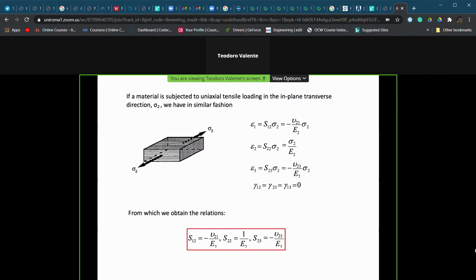If instead we are going to apply a tensile load in the transversal direction, that is in direction number 2, we do have, again in a similar way, the possibility to define the 3 strains according to the 3 axes 1, 2, 3, a shear coupling again not being present. And so what is leading now is this expression, which comes again from the application of the linear Hooke's law, and then the possibility to have the contraction in the other directions defined by the relative Poisson ratio. And so, this simple equation being valid, this means that we can also define the values of the terms S12, S22, and S23.